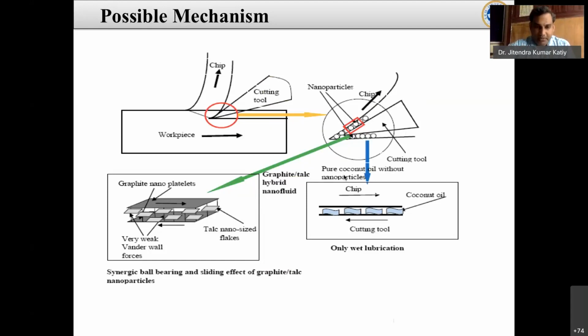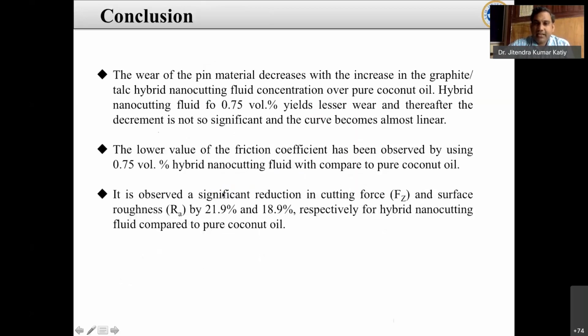So this is the possible mechanism which I proposed, and that paper is published in the Journal of Manufacturing Processes. This is the overall conclusion which I observed: a significant reduction in cutting forces and surface roughness, by 22% in cutting forces and 19% in surface roughness, with this hybrid nano cutting fluid. Lower values of the friction coefficient were observed with the 0.75 volume hybrid nano cutting fluid in comparison to